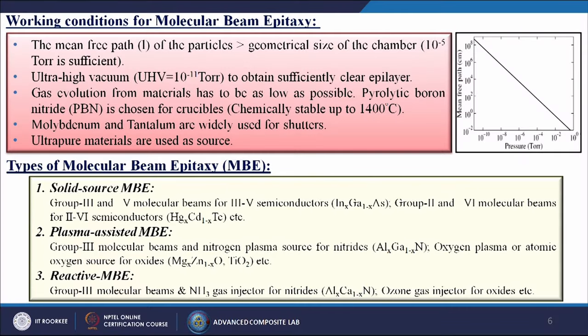Next, ultra high vacuum, generally UHV, is 10 to the power minus 11 torr, to obtain a sufficiently clean epi layer. Gas evolution from materials has to be as low as possible. Pyrolytic boron nitride, PBN, is chosen for crucibles, chemically stable up to 1400 degrees centigrade. Molybdenum and tantalum are widely used for shutters. Ultra pure materials are used as sources. So, these all are the working conditions for this particular technique.